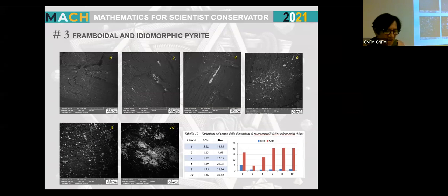If I have to consolidate the wood matrix, generally with polyethylene glycol, for a correct conservation intervention, I need to remove the iron present in the wood with the use of a chelating agent. Here I had the opportunity to conduct an extraction test for iron chelation with set immersion times. The results visible in the image show how the concentration of pyrite granules, almost absent in the sample at time 0, untreated wood, increased over the days until it occupied on the 10th day about 50% of the analyzed surface.